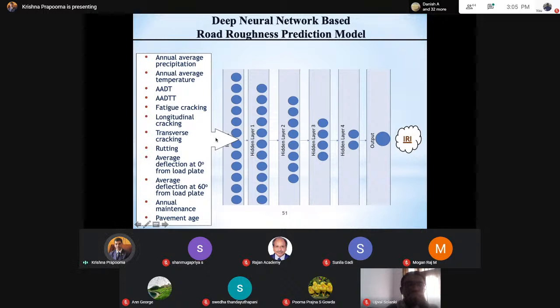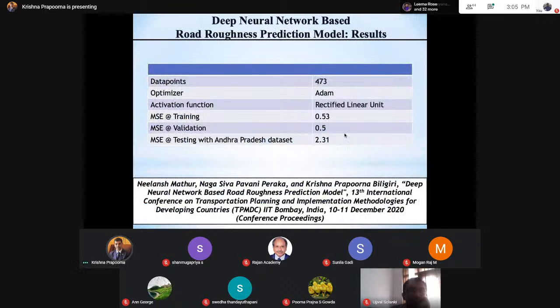Again, we used a deep learning network, and we were able to capture all of these. We input that. There are different layers, and we calculate the international roughness index. That's what we were aiming at, because the LTPP database captures IRI. They have measured IRI, but what happens after a few years, we are not able to do that. So our network can do this. This was recently presented by my student Nilansh, BTech. It's actually a BTech project that he did. Pavements is our PhD. So it was just recently, just last week, we presented this.